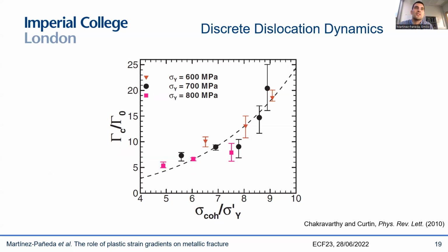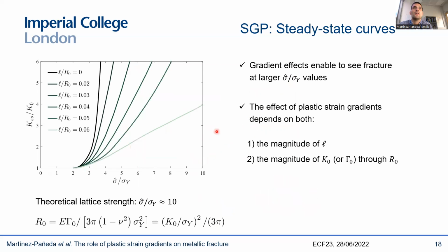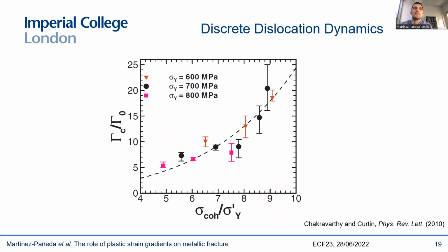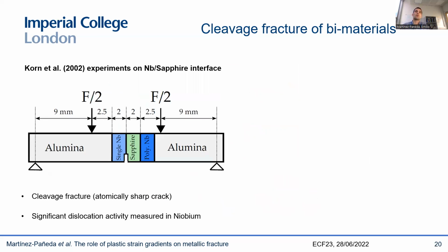So these are discrete dislocation dynamics simulations, and you can see that somehow they will also be able to capture eventually fracture near this region of 9-10 times the yield stress. So it seems to agree pretty well with some of the predictions of strain gradient plasticity. And this framework allows us to rationalize many of the experiments that I showed you before. Let me discuss some of them.